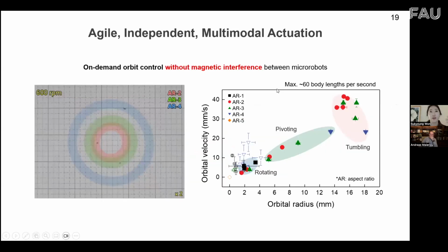And for the collective behavior, these orbital maneuvers were achieved without magnetic interference between the robots due to the high actuation speed of up to 60 body lengths per second for the tumbling motion case. Additionally, robots with different aspect ratios experience varying centrifugal force, enabling the independent multimodal actuation of these multiple magnetic robot systems.